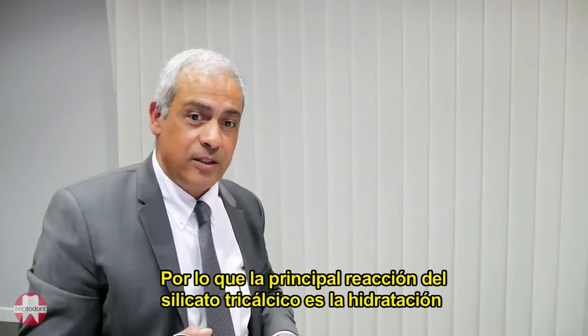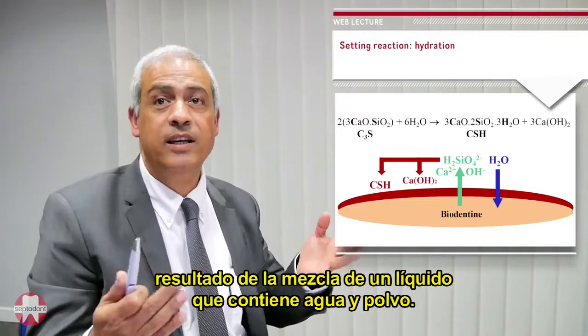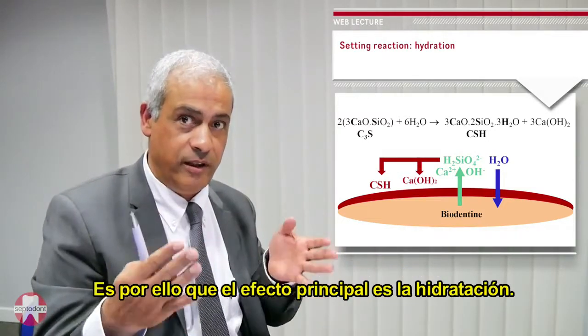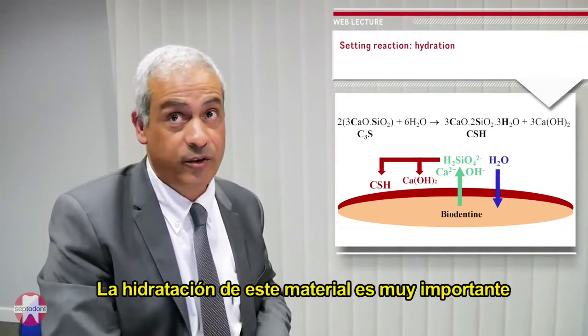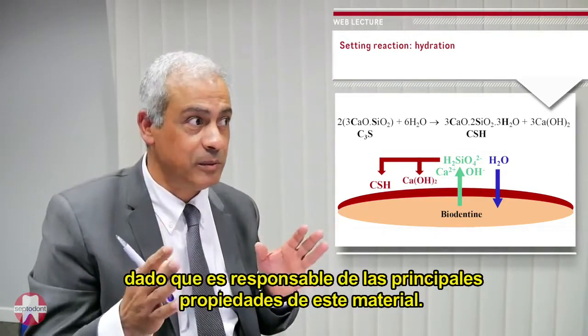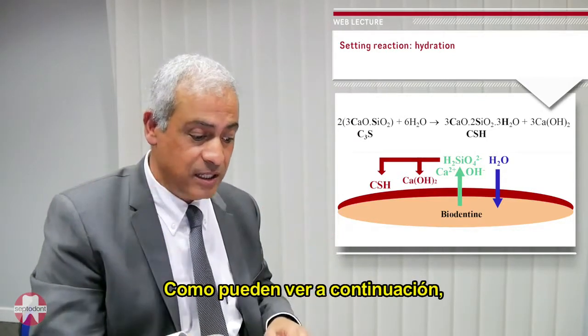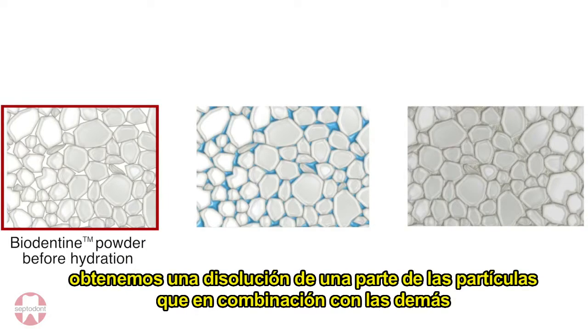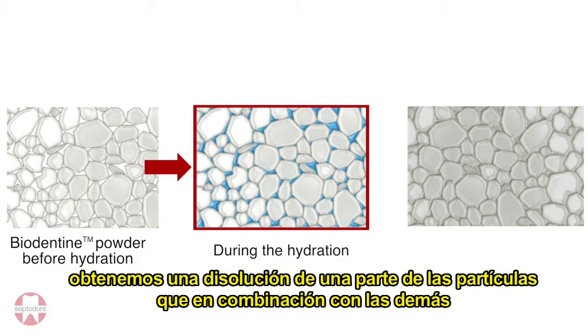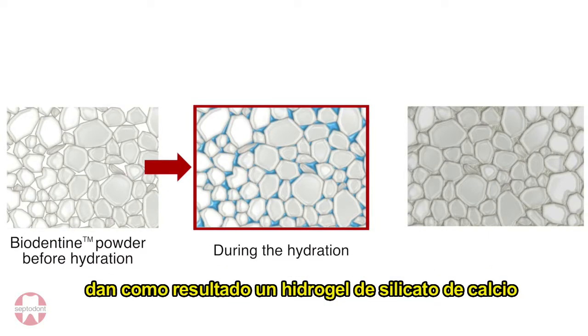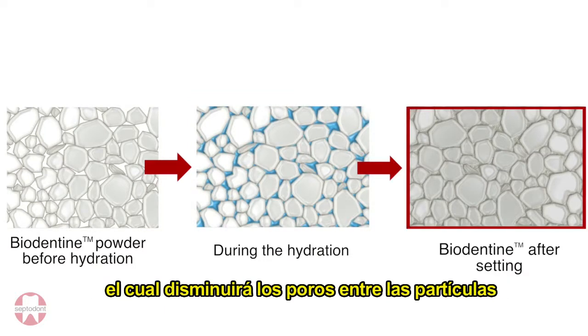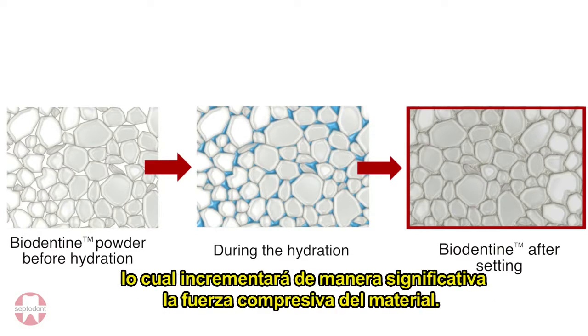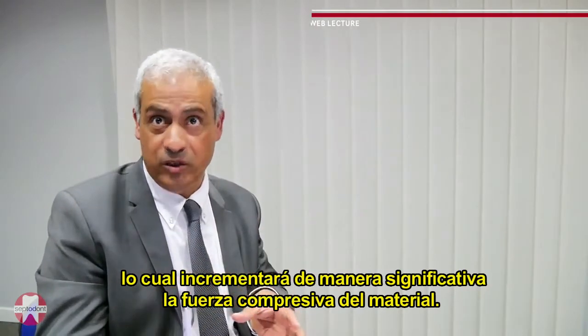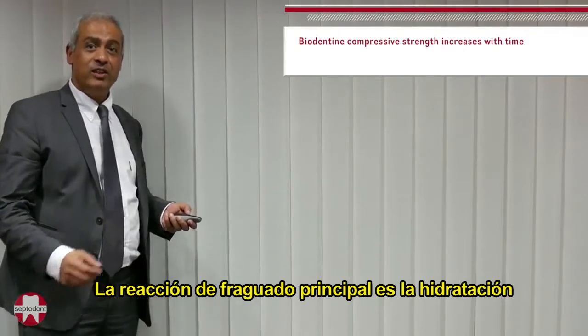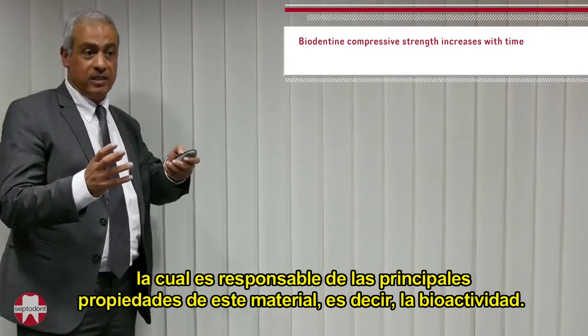For tricalcium silicate, the setting reaction is a hydration reaction. It is simply a mix of a liquid containing water and a powder. The hydration of this type of material is very important because it is responsible for its major properties. When you mix the material with the liquid, you get a dissolution of part of the powder particles. These precipitate on the other particles and within the spaces, leading to the formation of calcium silicate hydrogel. This decreases the pores between the particles and significantly increases the compressive strength of the material. So the setting reaction, which is the hydration, is responsible for the major properties of this type of material, that is, the bioactivity of this material.